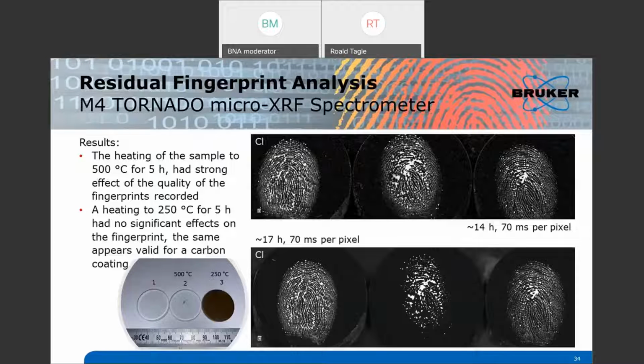So, now you see the results of our experiment. Remember what we were saying before. The first measurement at the top, samples 1, 2, and 3: untreated, original. Second measurement at the bottom. First, untreated, original. Second, heated up to 500 degrees for 5 hours. Third sample, heated up to 250 degrees for 5 hours and coated with the carbon coater of the SEM.